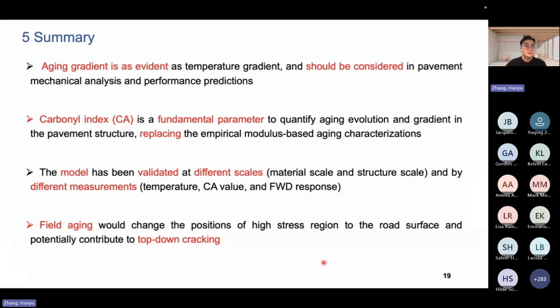So yeah, here's a summary for the modeling part. First, aging gradient, like we observed in the field, is as evident as temperature gradient, and we should consider it in pavement mechanical analysis and performance predictions. Second point is that carbonyl index is a fundamental parameter to quantify aging evolution and aging gradients in the pavement structure. So it can replace the empirical modulus-based aging characterizations.